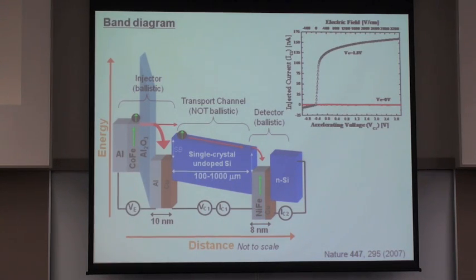And so their mean free path, the inelastic scattering rate, if you will, is dependent on the relative orientation between the spin polarization of the electrons after they've traveled through all of the silicon and the ferromagnetic magnetization. Okay, so what that means is that if we're injecting spin-up electrons, if the spin is maintained in the up direction and the magnetization of our ferromagnetic detector contact is also up, then the mean free path will be relatively long, and the probability that the electron will pass ballistically through this ferromagnetic thin film and over another Schottky barrier on the other side into the conduction band of a second piece of silicon will be relatively high. If, on the other hand, we have an anti-parallel configuration, we inject spin up, but we have a detector magnetization that's down, then we'll have a shorter mean free path, stronger inelastic scattering, and the rate of electron injection into the second piece of silicon will be low.